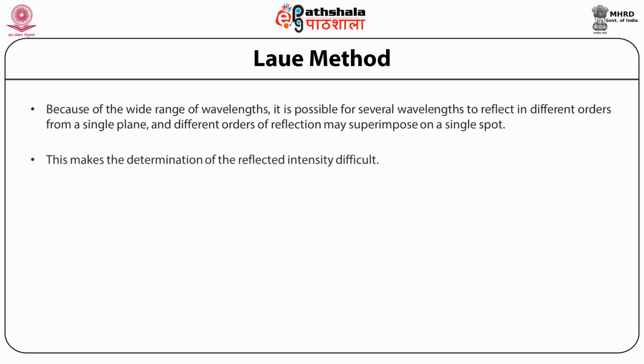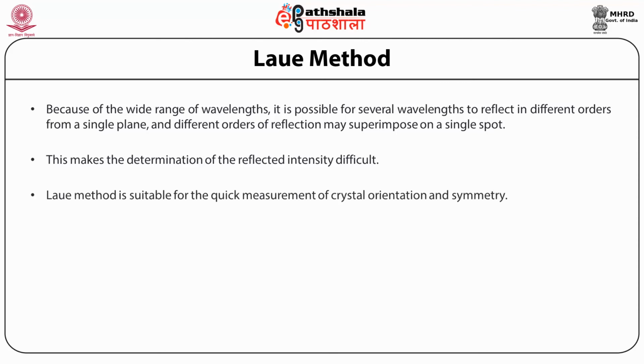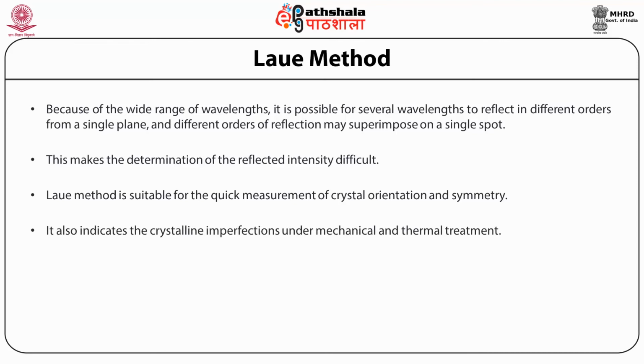This makes the determination of the reflected intensity difficult. Laue method is suitable for the quick measurement of crystal orientation and symmetry. It also indicates the crystalline imperfections under mechanical and thermal treatment.